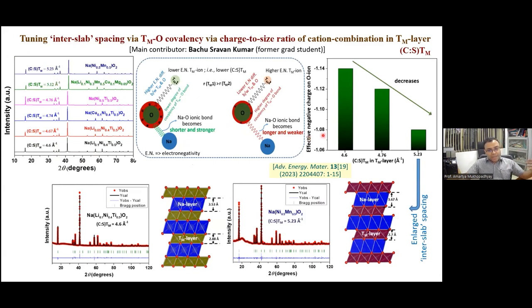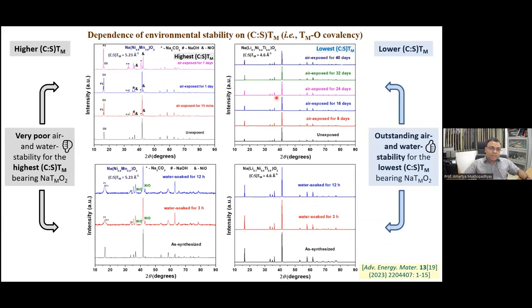And the DFT calculation by my collaborator from Chemical Engineering, IIT Bombay, Professor Abhijit Chatterjee, also showed that it goes with our hypothesis that if the charge to size ratio is lower, the effective negative charge on the oxygen ion is higher, and hence the sodium oxygen bond is stronger and the interslab spacing is narrower. So then it will be difficult for the sodium ions to come out spontaneously when exposed to moisture. Now, if that is so,